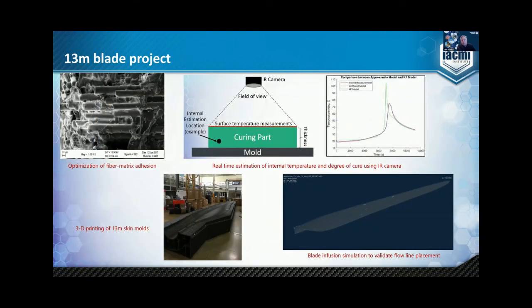I talked about the 3D printing of the skin molds, using simulation software for blade infusion, and then a novel technique devised by Vanderbilt University to measure surface temperature and correlate that to degree of cure in the part. So when you can see through the bag, you can measure the surface temperature and then correlate that to degree of cure, so you know when you're done.